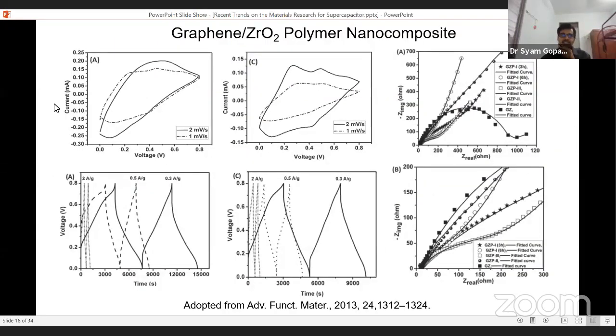And when we compare, these are the results of this particular graphene zirconium oxide polymer nanocomposite. But in this case, when we look at the CV, what we are observing is that some redox peaks are being formed. That means from the normal supercapacitor behavior, this material is slowly changing to a battery-type material. So here we cannot take the instantaneous capacitance. We should take the average capacitance, so that this material could be considered as a supercapacitor material. So this is how research in supercapacitor materials is now progressing.